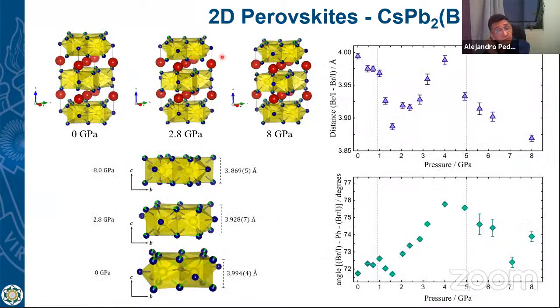And when you study how these octahedra change with the pressure, we can see that in the first transition, there is a change in the lead-bromine/iodine distance, and in the lead-bromine angle. This distance is changing, and this angle is also changing. Inside of this structural phase, there is no structural phase transition, but there is a change here.